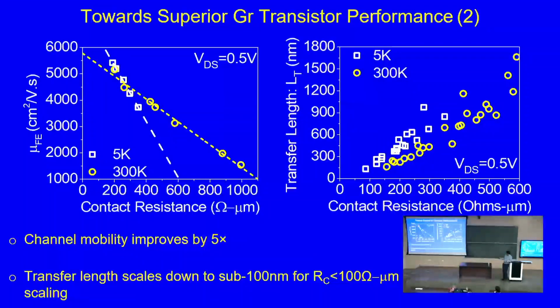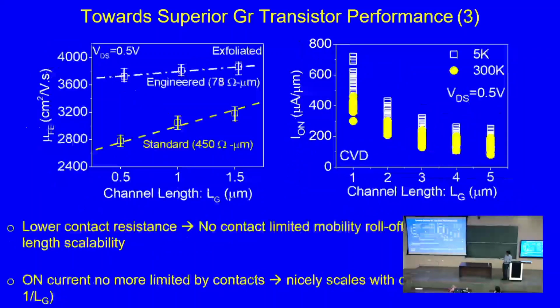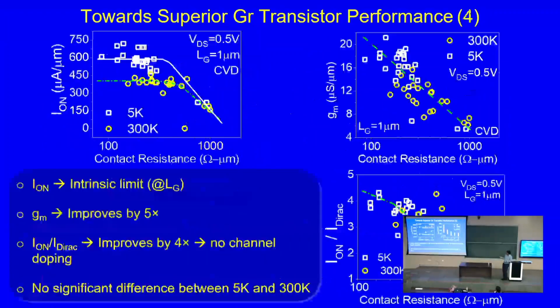As you scale the contact resistance, as you see in all the experimental data, the mobility gets better and the transfer length goes down. The mobility does not roll off as a function of channel length. You get the maximum out of the transistor in terms of drive current. If you see, after a certain point the current starts saturating, so you get the best you can out of the transistors. And the Ion by I Dirac also improves.